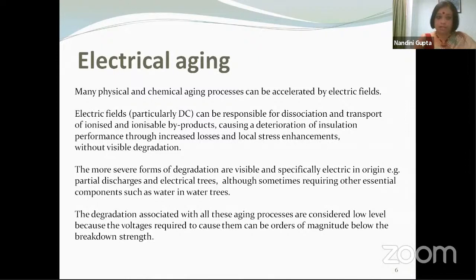There will be byproducts. When you apply an electric field, you add extra energy to the system, and then that can cause formation of ions. So neutral molecules will break up into ions, and under the application of the electric field, these ions will be accelerated by the electric field. They will acquire energy from the electric field. So firstly, charged particles will be produced, and these charged particles will be accelerated in the electric field. Once that happens, they contribute to losses. They contribute to losses simply by moving through the material, simply due to transport through the material.